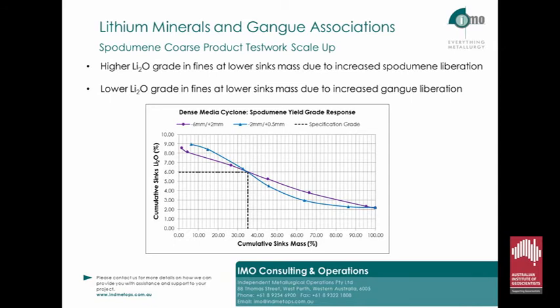The fines grade, however, dips here as spodumene recovery is higher up front, which is as we move down the graph, and gangue mineral liberation, which goes hand in hand with spodumene liberation, has increased. As the SG decreases and the sinks mass increases, liberated gangue minerals will report to the sinks. However, for the coarse fraction, these gangue minerals will contain spodumene, and therefore the lithia grade will ultimately be higher. As you can see, the lines cross over. At 100% recovery, we're back to the head grade.